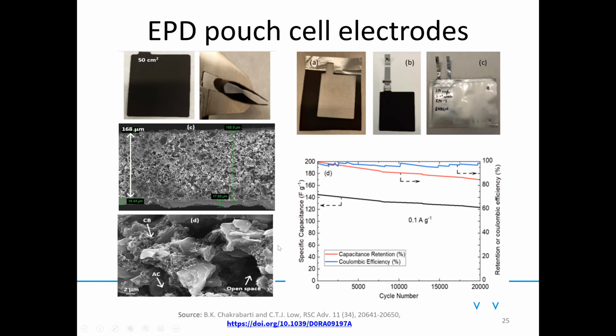We didn't do any direct particle size distribution analysis, but I agree with what you're saying. Particle size does affect the deposition to an extent. The activated carbon particles are larger, some microns, whereas the carbon blacks go into the hundreds of nanometers range, and the PVDF, I forgot the size off the top of my head. They do affect how the deposition occurs and the porosity of the sample, as you're rightly saying. Porosity, yes.